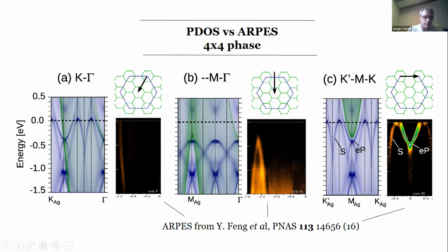Another direction, the M-gamma direction: again, the blue is the folded band structure of the 4x4, and on top of it I put the band structure of the silver. We can see that this feature that we're finding here is perfectly correlated with this band gap that we see here. It's the edges of this band gap. So again, we really believe that they're looking at some very intense silver state, which coincides with the edges. This direction, K-prime-M-K, where they said that they had two Dirac cones, is the most interesting one because it's mostly a gap.